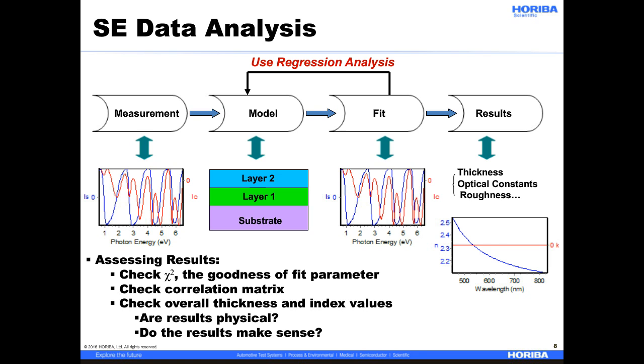So when I say, are the results physical? Well, there's certain optical constants that you would expect for certain types of materials, so you want to make sure that your optical constants are behaving as they should. And when I say, do the results make sense? We're checking the error bars on the numbers, we're checking the numbers themselves just to make sure that they're in the range that we expected, and we're checking the overall results to see, is this what we would expect for our sample?